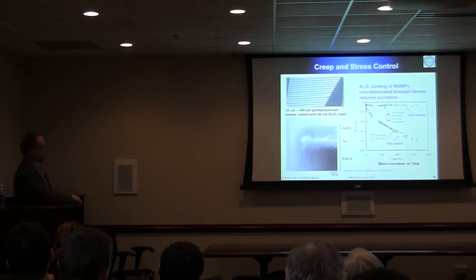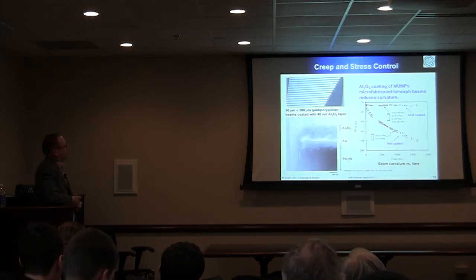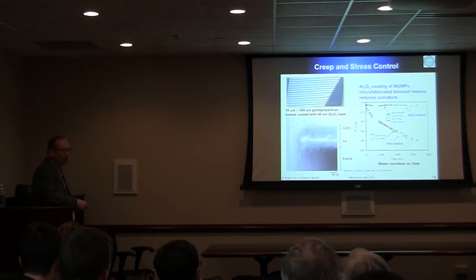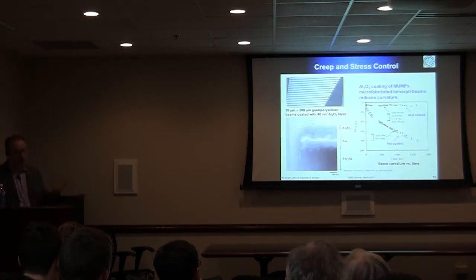Now, one interesting application of this coating is also for creep control, stress control, relaxation in films. So here is an example of a classical polysilicon beam coated with gold. Over time, the residual stresses are such that the beam curvature will change. If you coat it with ALD, encapsulated with this hard shell aluminum oxide, you can find a way to control this over time. This is important for many applications. Here is a corner of this polysilicon beam just to show conformality. It's an important problem that people typically don't talk about, but it's there. So you need to figure out how to control it.